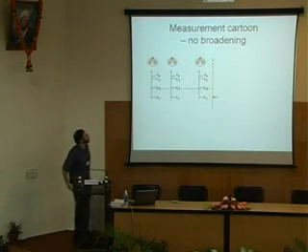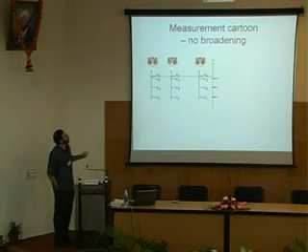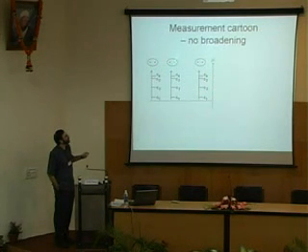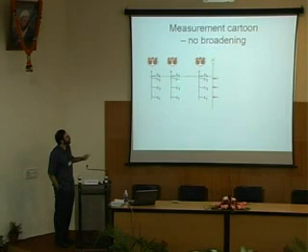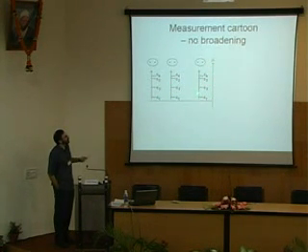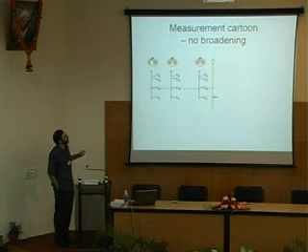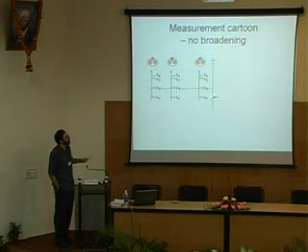Cartoon. So here I'm assuming that we have 3 pairs of dopants, and they're all behaving exactly the same way. So here are our particle in the box, and all the epsilon 1s, epsilon 2s, epsilon 3s are lined up with each other. As we then ramp the voltage V tip, there's our chemical potential moving. We see that here 3 electrons go on at exactly the same time. Exactly the same time until each one of these is totally filled with 4 electrons. Every time that happens, we see a peak in our capacitance measurement, and that's plotted over here.